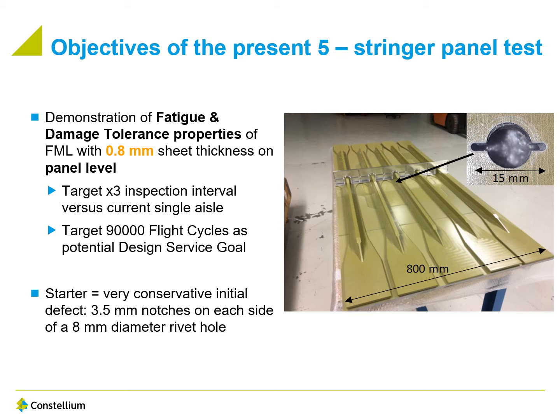You can see here the panel. It's made of FML with a 2024 sheet and 7075 stringers that are bonded onto the skin. We have put an initial defect that is very conservative. It's over a rivet hole. We have water cut 3.5 millimeter notches on each side, and it makes a 15 millimeter defect. A typical defect from a hole would be a 1.27 millimeter flaw. So here we are really very conservative in terms of starter notch.